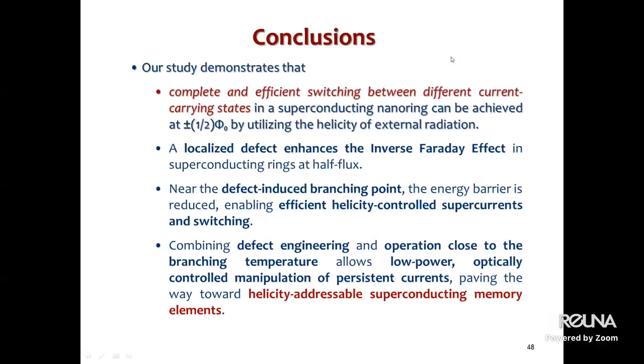So I would say from one side, it's better to have a higher free energy barrier. In this case, of course, there is less probability, let's say the system is more robust. Less probability for the system to occasionally move from one side. For example, we submitted counterclockwise illumination and obtained clockwise current. And we don't want to obtain a counterclockwise current. So it may happen due to some fluctuations. These fluctuations are strongly reduced with the increase of the barrier between these two states. But from another side, the higher this barrier is, the longer time we need to perform the switching, especially taking into account the engineering application of this effect.